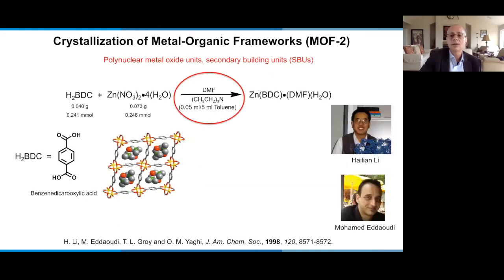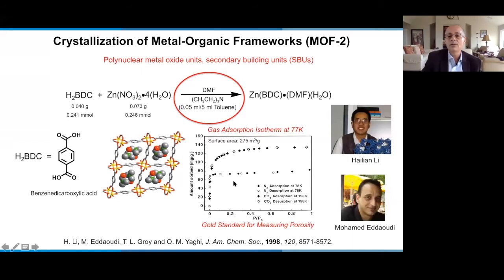Well, to prove their porosity, you have to measure the gas sorption isotherm. This is the only way of proving permanent porosity, short of a crystal structure of the evacuated framework, which we later showed could be done. But in 1998, we reported the gas adsorption isotherm of this MOF, which had DMF molecules in its pores. Once you remove the DMF molecules, you can, as shown here, introduce nitrogen or CO2, and as shown with the open circles, it is completely reversible for gas uptake. This is the gold standard for measuring porosity, and it proved for the very first time that these structures are permanently porous. And this, while it went unnoticed for a year or so, became really the beginning of MOF chemistry in terms of proving the porosity of their structures.